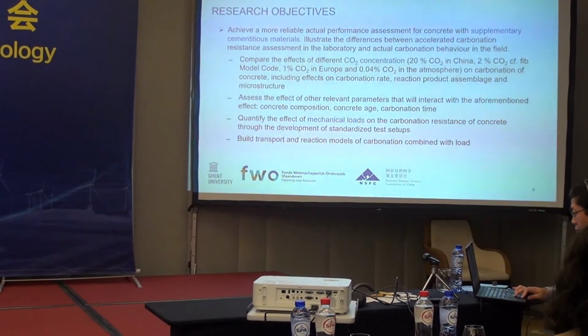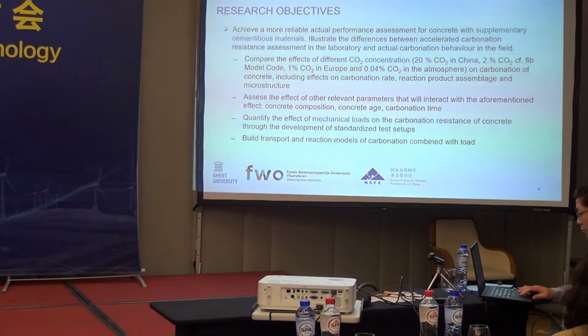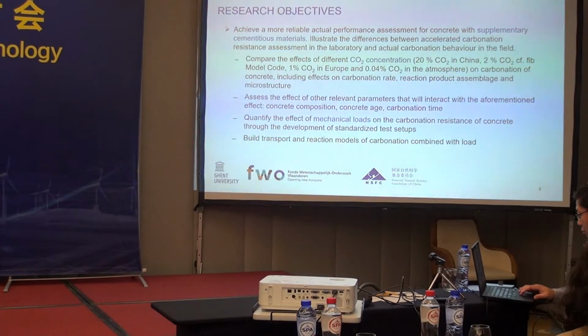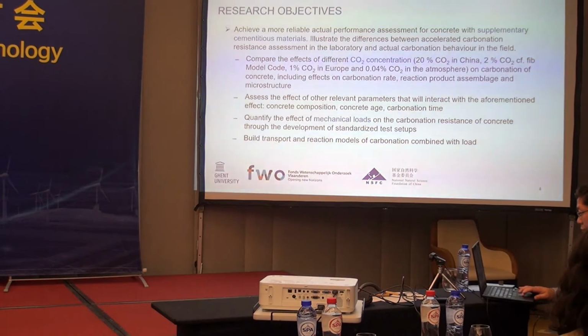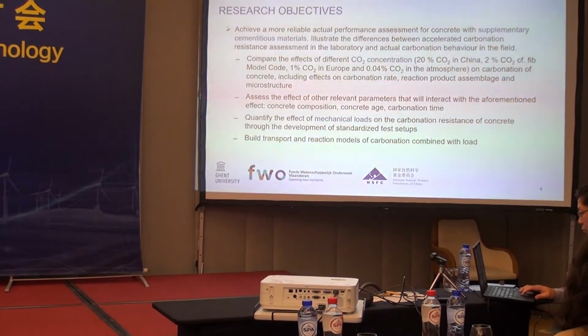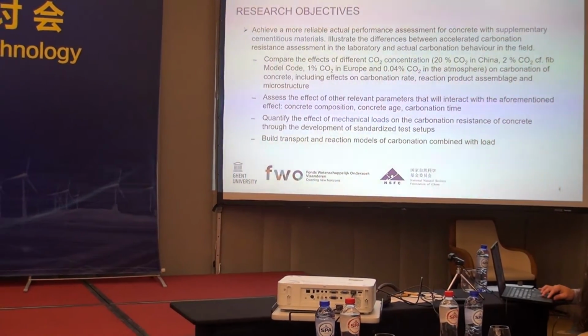Okay. So the problem, of course, is here that we are looking at concrete, like I said, with different supplementary cementitious materials. And in normal Portland cement concrete, you have quite some buffer because it has a high calcium hydroxide concentration. So when carbon dioxide is entering into the concrete, it reacts with this calcium hydroxide, forming calcium carbonate. But since there is a lot of calcium hydroxide, this ingress, this carbonation process is quite slow.